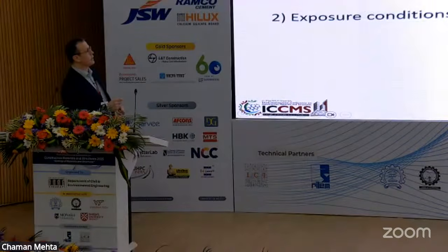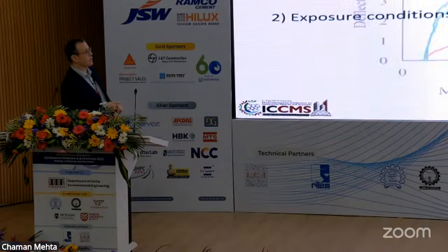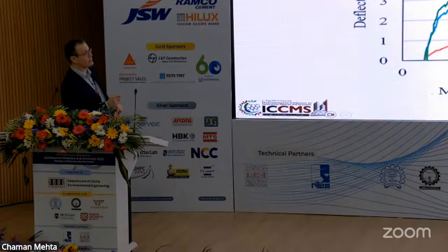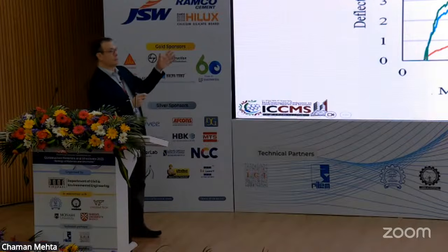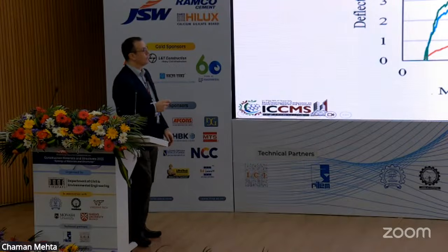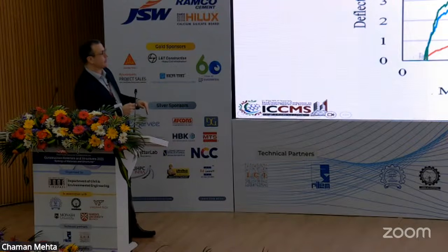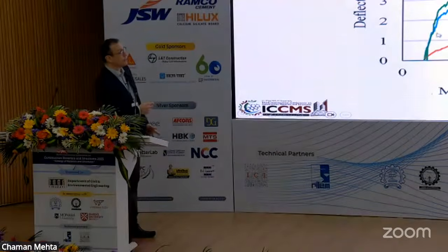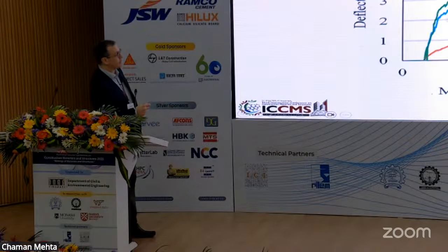I'm going to show you the results now for one sample, a composite slab with the sheeting at the bottom, sealed on the sides, and another sample sealed everywhere on the top. We're looking at this simply supported beam, where a 3-meter span is typical for this kind of dimensions. If you sealed it at the end of the day of casting, this is where you go. Why do we do that? Because we want to eliminate all the drying effect. You can really kill time effects a lot if you limit your drying effects. If you keep it exposed on the top, you build up all this deflection here, and again, it's due to the gradient you saw before.